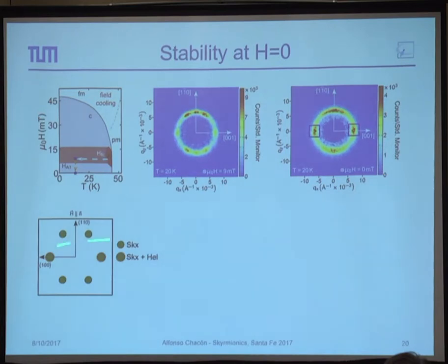So for our studies, we prepare the sample as mentioned before. We could always go to the skyrmion lattice before deciding where exactly to plot the phase diagram. We performed different tests. We went through different fields and checked how much volume of skyrmion lattice we obtain at those fields, and after defining what the optimal field is, we then pull down the sample again, go to zero field, and just wait, and measure it over time, every 5 or 30 seconds, depending on how much intensity we're getting.